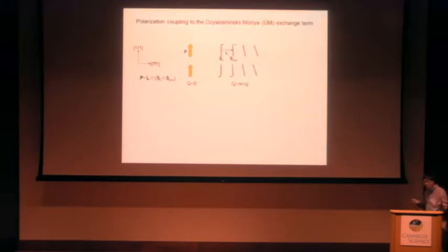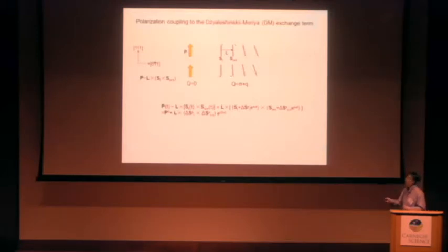So similarly, if we consider spin wave excitations, well, for classic spin wave theory, the spin wave excitations are actually spins precessing around the original direction. But in our case, we can just think about the in-plane component, because actually, if you look at the out-of-plane component, their effect tends to cancel out. Okay. So if you look at the spin fluctuations, basically, we can just put a simple model, put the time dependence of spin vectors into this formula, and then we get a time-dependent polarization.